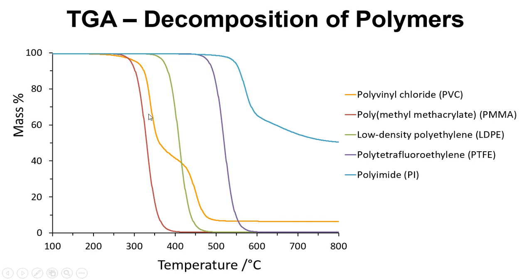PVC, we can see it breaks down in a couple of stages, and it doesn't go down to 0%. So maybe there's some filler in there, or maybe there's some char that's formed that doesn't decompose.